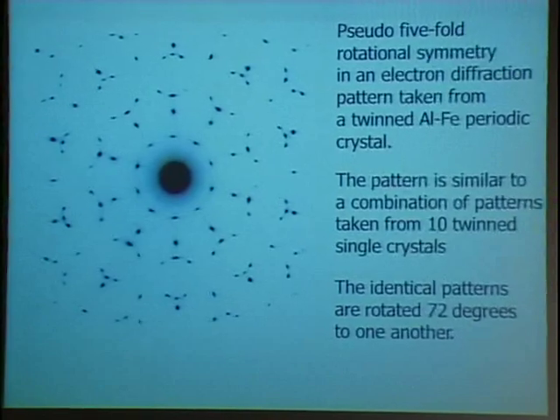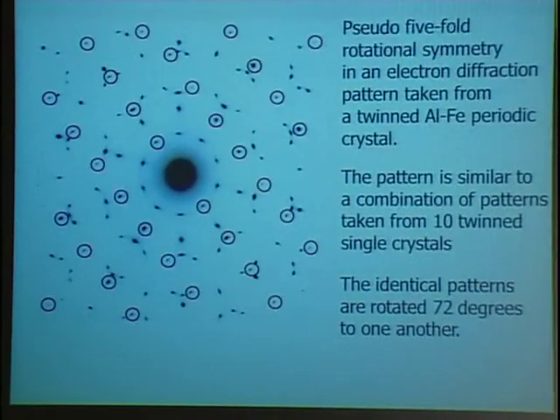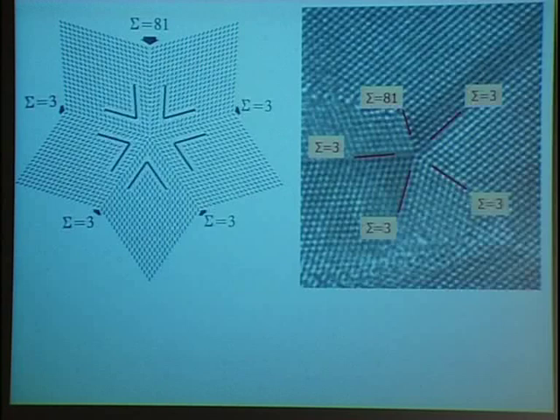Okay, so this is what I thought, and I was looking for the twins. Here's just one. Here's another lattice image of five-fold twins. This is in diamond. This is also abundant. And here you can see the atomic plane. Each one of these is a mirror plane. It's a mirror boundary. So if you follow this line or this plane of atoms, here is this plane of atoms. So this is a mirror, and this is another mirror. There are 5 twins here, and we shall skip the sigma notations now.